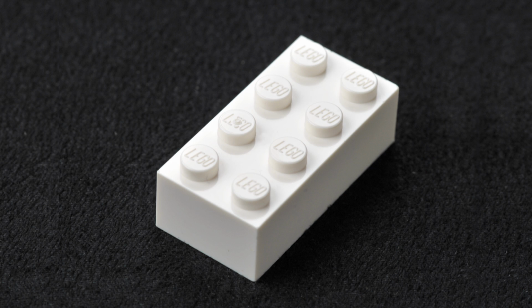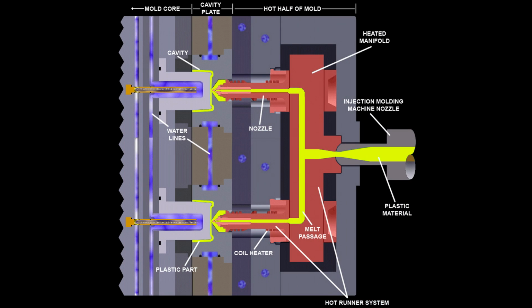One truly impressive example of injection molding is the Lego brick. You can see the injection point in the middle of the stud. But this is not from a gate or a sprue. The Lego molds inject plastic into cavities using hot runners. With hot runners, the distribution network is heated and stays molten. This means the molded bricks are ejected in a ready-to-use state because they do not have to be manually removed from gates or sprues. Hot runners also result in a more subtle blemish at the injection point. The downside is that this setup is much more expensive than a traditional cold runner system.